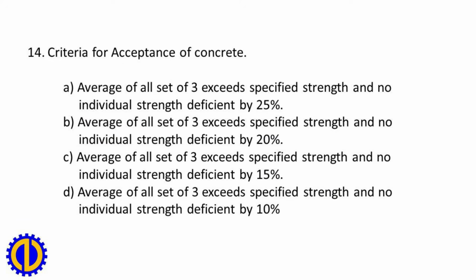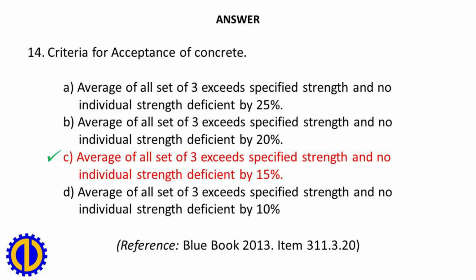14. Criteria for acceptance of concrete. A. Average of all sets of 3 exceeds specified strength and no individual strength deficient by 25%. B. by 20%. C. by 15%. D. by 10%. C. Average of all sets of 3 exceeds specified strength and no individual strength deficient by 15%. Reference, Blue Book 2013, Item 311.3.20.